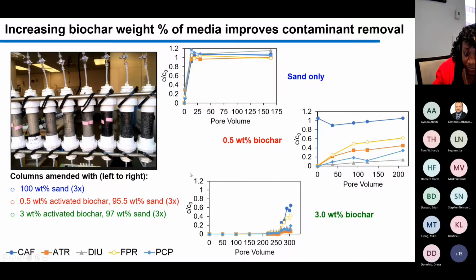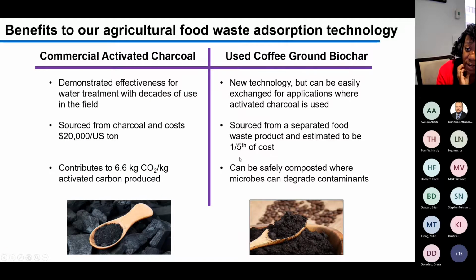So if you could extrapolate that further, you can hypothesize that, to a certain extent, again, without impacting the physical flow of water through these systems, you could add a lot more biochar and get a lot longer removal of these contaminants in water. So the data that I'm showing here is for, of course, select trace organic compounds, and we're going to do some further probing into abilities of the biochar to remove other types of contaminants like trace heavy metals. So we're really excited about the preliminary data that we've collected so far in mimicking infiltration stormwater systems like rain gardens, and especially how it compares to materials that are already used in water and wastewater treatment, such as commercially available activated carbon or charcoal.